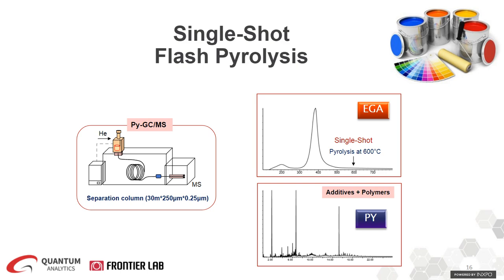As also mentioned, besides flash pyrolysis, this is a multi-mode furnace, which allows you to perform multiple analyses. So you could do thermal desorption, thermally extracting all the volatiles, and also perform flash pyrolysis at the same time. Using F-Search, I can also mention that you could create your own user library. A lot of our customers create their own user library. They run standards and references and save that maybe as a good sample, and then they could compare it to the other samples that are submitted, or perform failure analysis to identify, for example, some additives were found in sample A, but they were not found in sample B, just as an example.